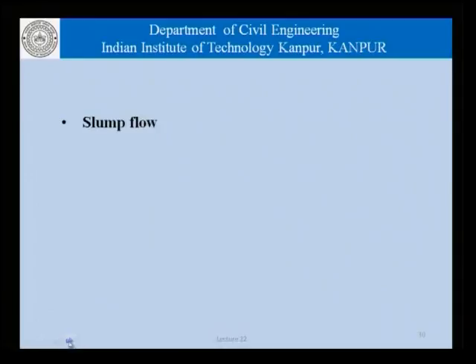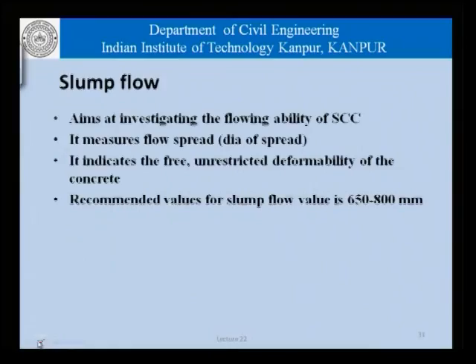Coming to the slump flow, the test aims at investigating flowing ability of the self compacting concrete and measures the spread, the diameter of the slump being a measure of that flowability, and indicates the free unrestricted deformability of the concrete. Recommended values of slump flow are in the range of 650 to 800 millimeters.